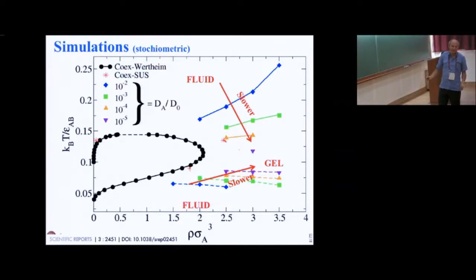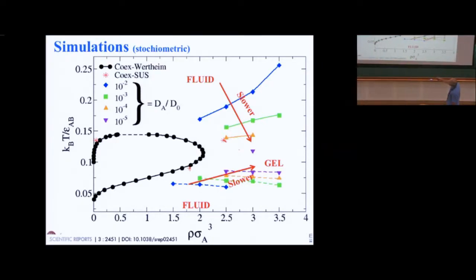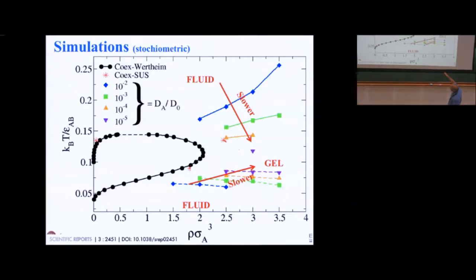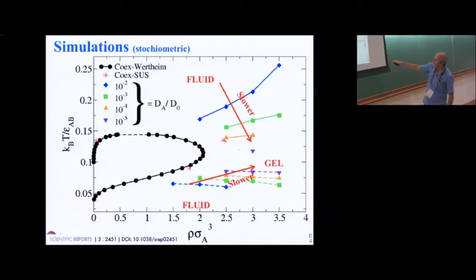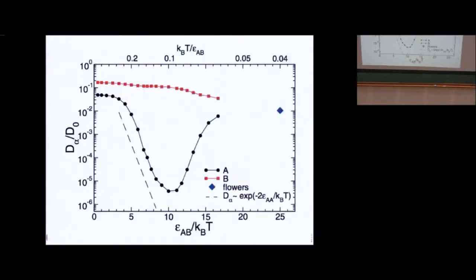And this is what we find if we do the simulation. This is the phase diagram, first of all. And you see that this has exactly the shape that we expected. This has a re-entrant phase diagram. The average valence goes from 4 when we are here, and then goes to 0 when we go to very low temperature. Those lines that I show you here are lines of equal diffusivity. And so from here to here, you go down in mobility a factor of 10, another factor of 10, another factor of 10. So the system gets slower and slower and slower, gels, and then gets faster and faster and faster, it becomes fluid again.